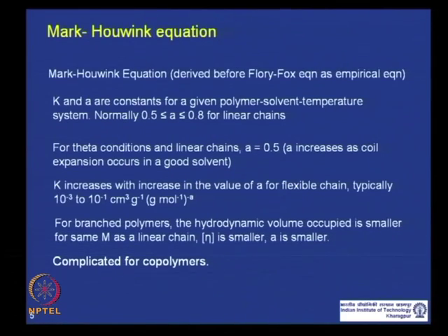For a linear polymer, A can never go down below 0.5, but if you have a branched polymer, it is more compact. So, if you compare the expansion factor with that of the unperturbed linear polymer chain, it may go down below 1. So, the intrinsic viscosity would be smaller as A becomes smaller.